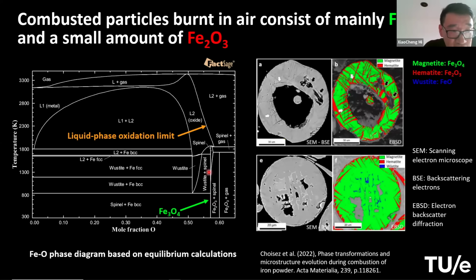In solid phase, this vertical line is Fe3O4, magnetite. That means if you can at maximum oxidize your liquid phase iron particle to this boundary, it's about the same as the stoichiometry of Fe3O4. And that is why we are seeing Fe3O4 as the main product after combustion.